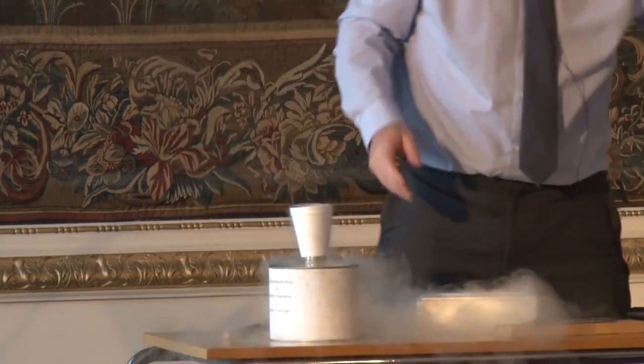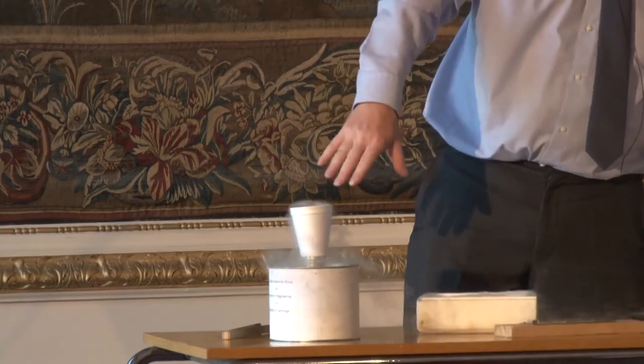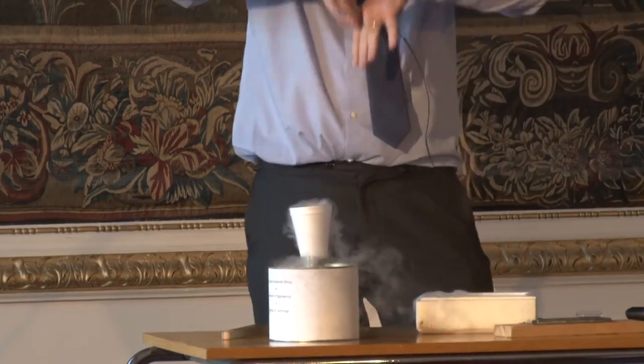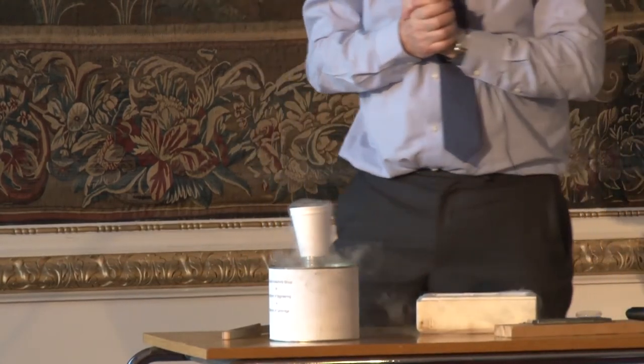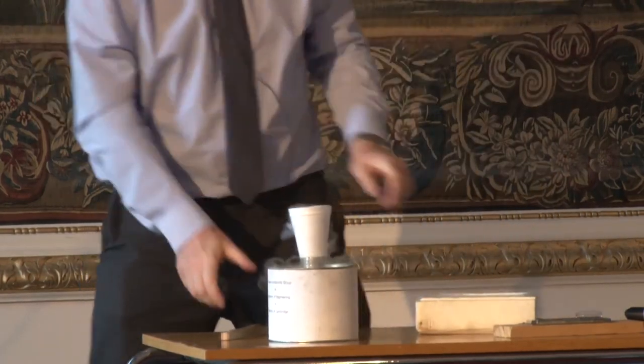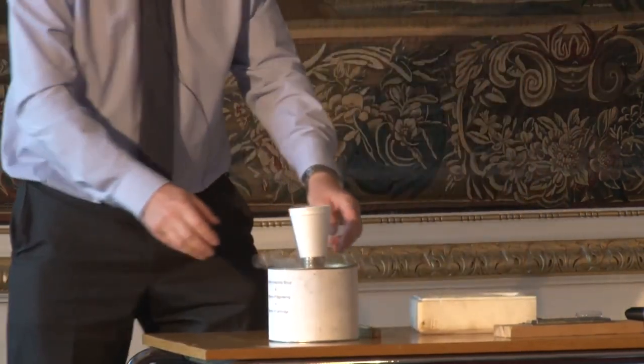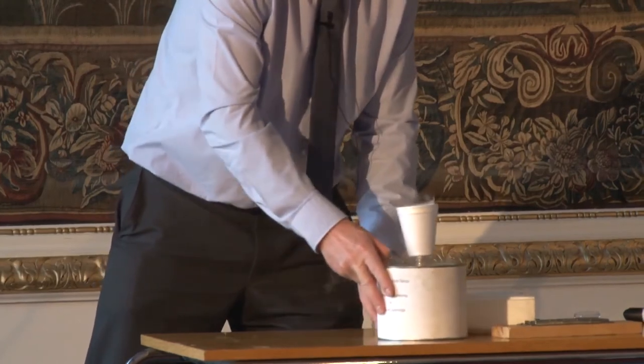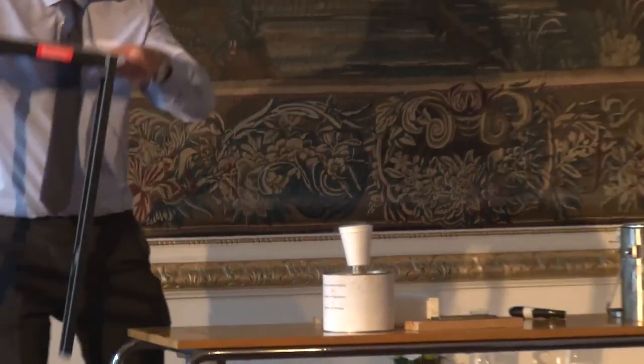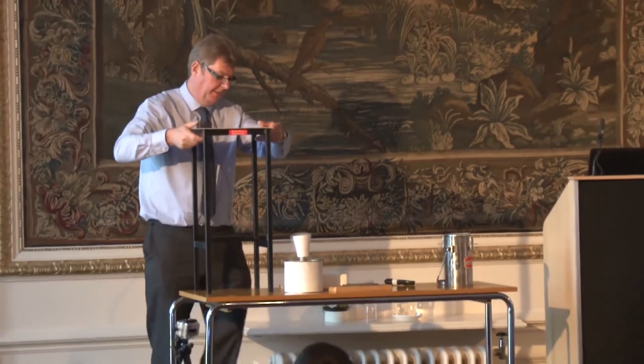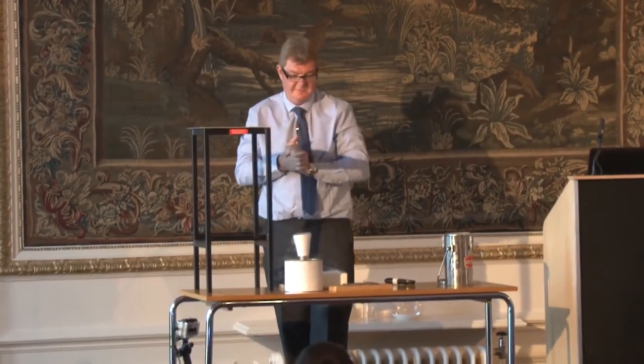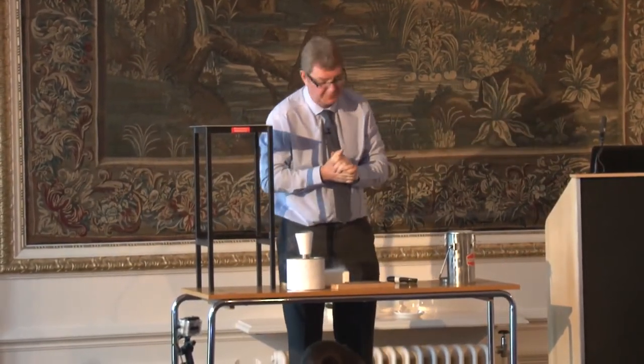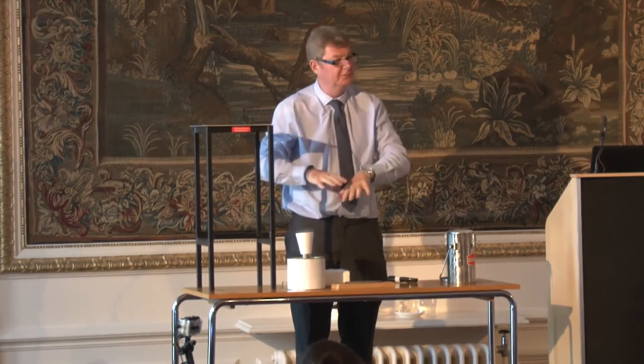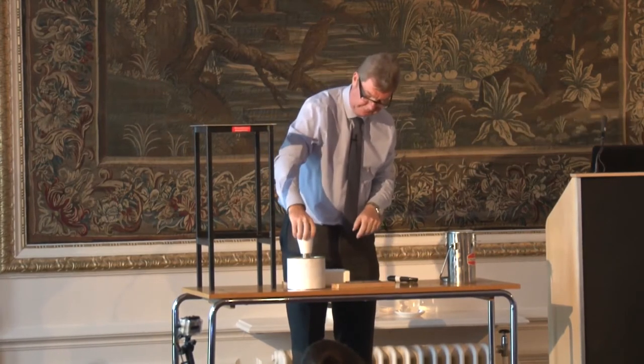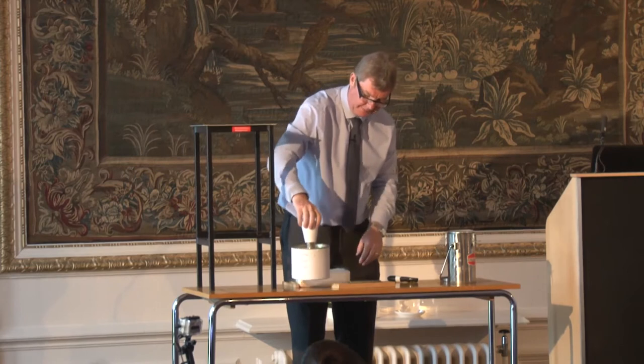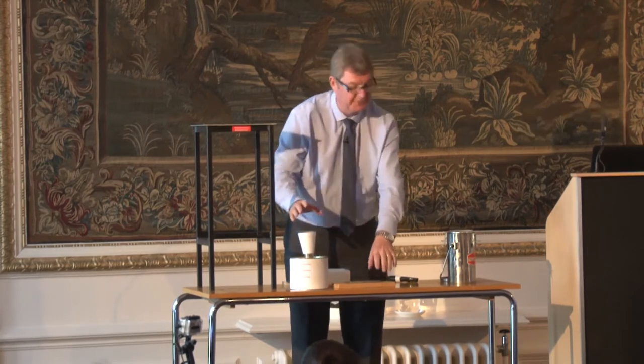So what I'm using now is temperature to pin magnetic flux in there, because the field lines will be frozen in when this becomes superconducting, and to see where it gets us. So there's a slight issue in that polystyrene is not the greatest load-bearing material that I've come across. And now these two should be a single system, so I ought to be able to pick this up, which I can. But now I've got to try and separate it.